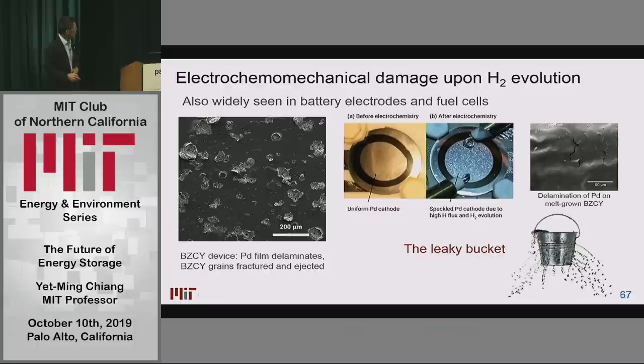What we found is that we at least figured out why the bucket is so leaky. It turns out that palladium, when you insert hydrogen into it, expands tremendously. And it's a mechanical problem.